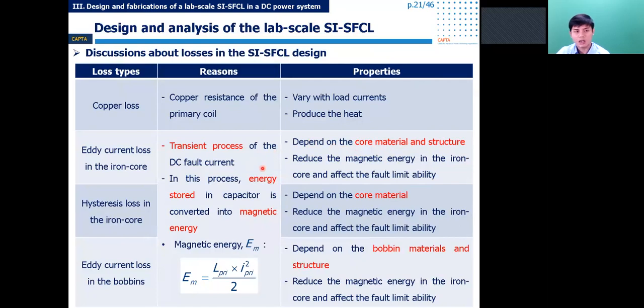In the practical design of the SI-SFCL, the loss is a very important factor. It can affect and reduce the magnetic energy during the transient fault. Thereby, it can reduce the inductance as well as the fault limiting capability of the SI-SFCL. There are three main losses in the SI-SFCL, including the copper loss in the primary coil, the iron core loss, and the eddy current loss in the coil bobbins. So next, I will design the iron core and the coil system based on the loss and the material cost problem.